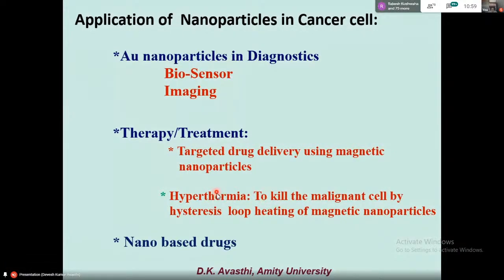That means you inject these nanoparticles, take them by magnet to the cancer cell, and then you magnetize and demagnetize from outside, which creates a hysteresis loop. And the hysteresis loop is nothing but heating of the magnetic nanoparticles which are in touch with the cancer cell, and they kill the cancer cell by heating. It is well known that cancer cells get killed at, say, typically 45 degrees centigrade or so. There are already nano-based drugs in the market, but they are very expensive. So a lot of research is required in this area to minimize the cost.